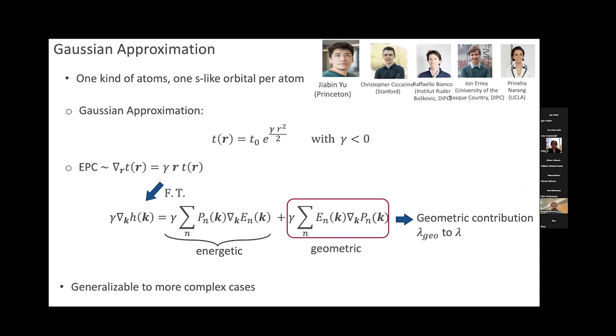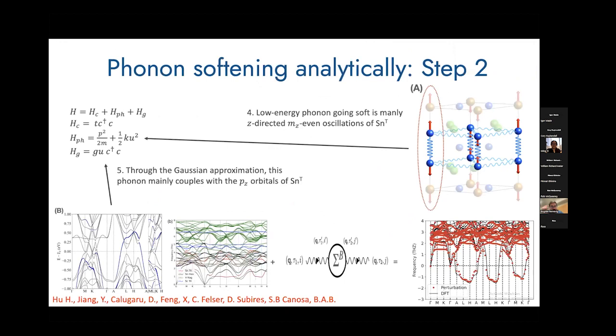And if you take this electron-phonon model, which is basically the even phonon within the unit cell coupling to the even combination of the electrons on the two tins, two trigonal tins within the same unit cell, then you're in business. You have an electron-phonon coupling that's analytically tractable. And now that you have this, you can compute the self-energy of the phonon induced by the bubble. Okay.